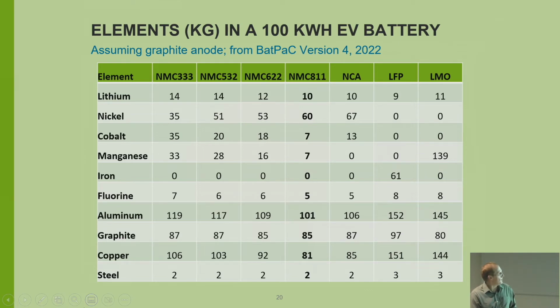Manganese is about the same. And your nickel is actually fairly high, about 60 kilograms. And again, nickel is not all that abundant. It's better than cobalt, but we would ideally like to get away from nickel and cobalt. And that's where we get into these other cathode materials, the lithium iron phosphate, which is basically just iron. There's lithium, iron, phosphorus, and oxygen. And the lithium manganese oxide spinel, which is manganese and lithium and oxygen.